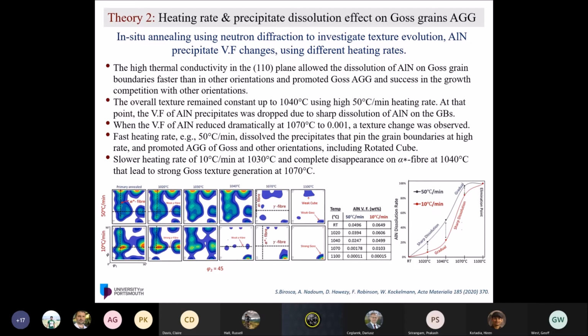So we did two sets of experiments there, one at high heating rate and one at low heating rate. The ODF I'm showing in the first row is at 50 degrees Celsius per minute, which is a high heating rate. You will see the alpha fiber and gamma fiber in the ODF going until 1070, when they dramatically disappeared, producing weak cube and weak Goss.